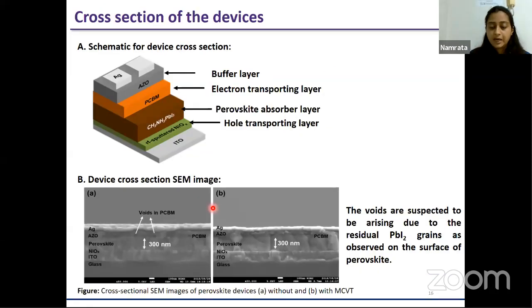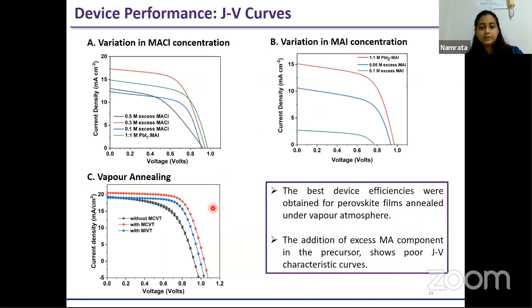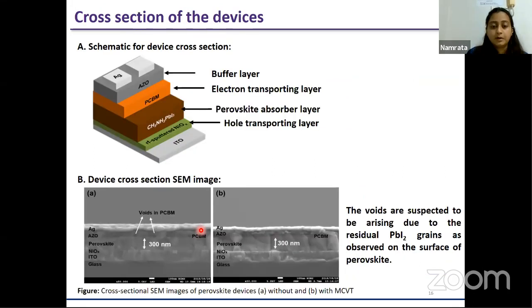So, as from the previous slide, we can see that out of all the JV curves, we have the best performance for the one with the methyl ammonium chloride vapor treatment. We further characterized the device, comparing only the perovskite that is annealed under the methyl ammonium chloride vapor atmosphere and the one which is annealed in its own ambient atmosphere.